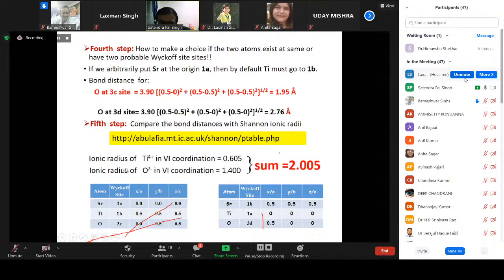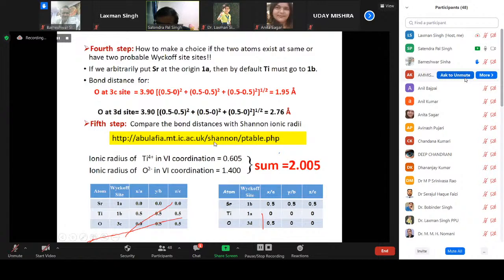And you can get the ionic radii online, from the Shannon tables. The ionic radius of titanium 4 plus is 0.605 in 6 coordination, and the ionic radius of O2 minus in 6 coordination is 1.40. If you sum up, it comes to 2.005. So you can compare this with the bond length obtained at each site. 2.005 is very close to 1.95, so the oxygen will go to the 3c site. So strontium goes to the 1a site, titanium goes to the 1b site, and oxygen goes to the 3c site.